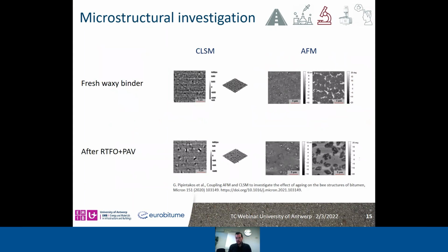In this slide, you can see for the binder an example of what advanced microscopic techniques can capture before or after aging. On the left, you can see topographic and 3D height images of a confocal laser scanning microscopy that we possess in our labs. And on the right, topographic and phase contrast images with atomic force microscopy or AFM. Some obvious observations before and after standardized simulation in the lab is that the number of bees is decreasing, for example, and this is confirmed from both microscopies.